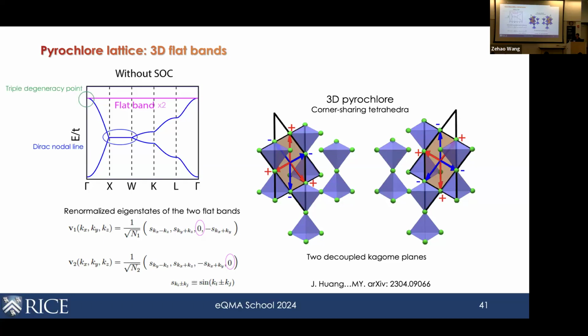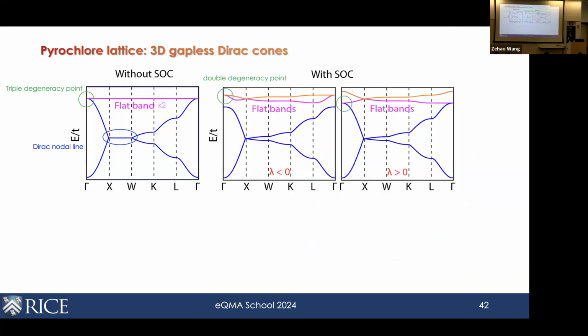So what else? From this, we can also read off another couple of interesting points. One is that there is a triple degeneracy point. There are 2 flat bands and the dispersive states that touch at the gamma point. And also along the XW direction of the Brillouin zone, there is a Dirac nodal line. This is the case without spin-orbit coupling. If you input spin-orbit coupling, a couple of interesting things happen. One is that there's a gap that opens at the gamma point, and you can get a double degeneracy point depending on the sign of your spin-orbit coupling.